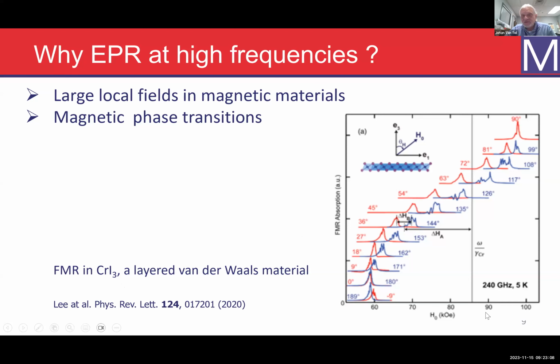In this case, it's plotted in kilo-oersted. It's not my usual thing, but our user decided to do that. So this is 6 Tesla and 10 Tesla. So you see that the local fields at the center are actually pretty large. And so we have like a 2.5 Tesla local field. It's kind of the exchange field at the sites of the chromium in this material.